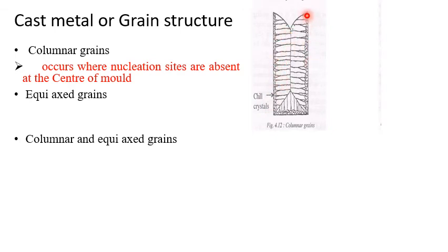The same thing here. The nucleation starts at the mold wall, and the grain grows in this direction. When these two grains, which are growing in the opposite direction, come and intersect here, then the growth of the grains is going to stop, and the same thing applies at the bottom also. So here the nucleation is going to start at the mold wall, that is heterogeneous, which means the nucleation is going to start with the help of a mold wall.